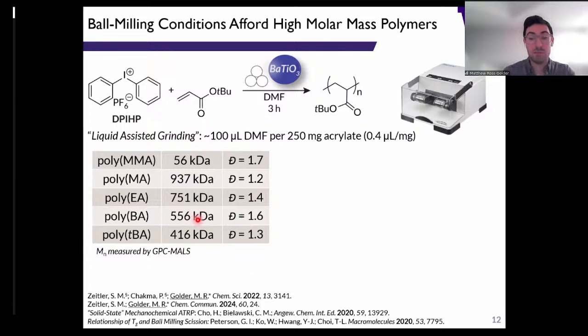Dispersities here are perhaps a bit lower than expected for free radical polymerization. We think that there could be some mechanochemical chain cleavage here at the high molecular weight end. But overall, these are really, really high molar masses that are oftentimes difficult to achieve in solution. And we think that some of the viscosity profiles here that are generated within the ball milling jars lead to a reduction in chain termination.